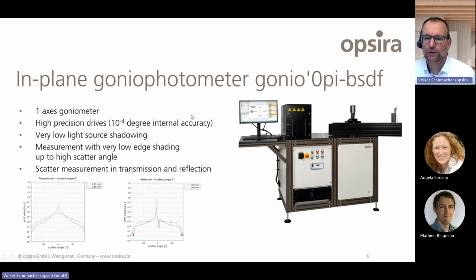The in-plane goniophotometer, gonio 0pi-BSDF, is a one-axis goniometer. We have here the sample, and here is the detector. The detector surrounds the sample, and the sample is illuminated from a light source, which is mounted here. We have collimated light which goes to the sample, and then it's scattered on the sample, and the detector surrounds the sample. It measures in transmission, and it also measures in reflection.